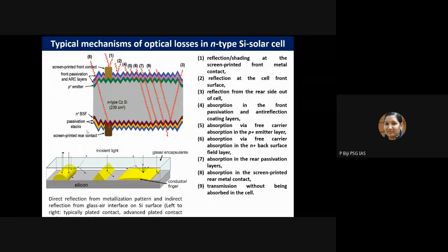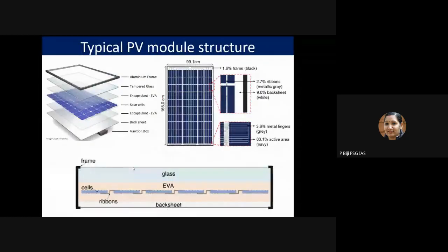Then the second one is an advanced plated contact. So that one, if you see, can reduce the reflection loss considerably. But it's still under development, because several other challenges have to be overcome. So you need advanced metallization technologies in order to fabricate such kind of contacts. And the third one is the generally observed screen printed silver contact. So that also has many disadvantages. As you see, there are several reflection losses happening in this case also. So you need some kind of advanced geometries, or you need some high aspect ratio features. So we'll see how such kind of metallization can be fabricated in later slides.